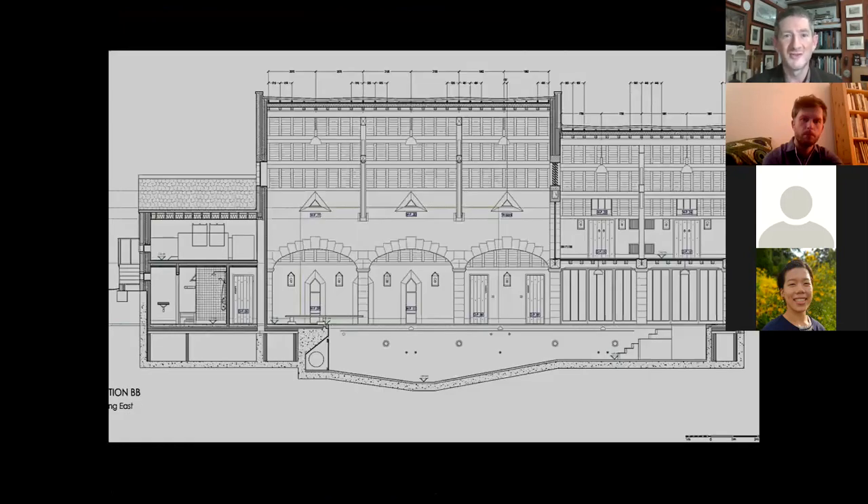Jonathan Norris's drawings for the pool building are fabulous. There are three things to point out: the wavy ridges are amply illustrated with the fairing pieces that vary in height. The engineers said these 18-inch columns couldn't be solid stone because the compressive strength wasn't sufficient to hold up the masonry above. They suggested a concrete column with stone stuck on all four sides. I said no. So each piece of stone has a hollowed out core, all stacked up one above the other, with reinforcement bars put down and concrete poured in. They are effectively a concrete column with stone cladding — but the stone is all in one piece with no joints, so you don't betray the composite structure.